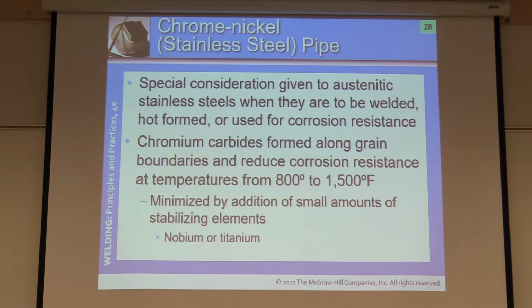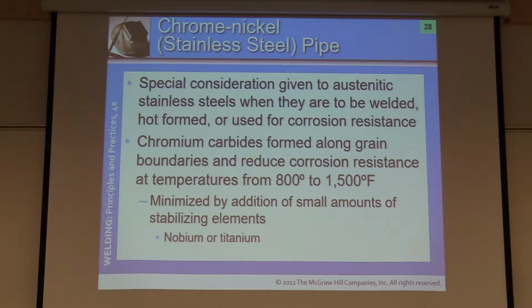Chrome nickel or stainless steel pipe. Special considerations are given to austenitic stainless steels when they are to be welded. They're hot formed or used for corrosion resistance. Chromium carbides form along the grain boundaries and reduce corrosion resistance at temperatures from 800 to 1500 degrees. This is minimized by the addition of small amounts of stabilizing elements, niobium or titanium.